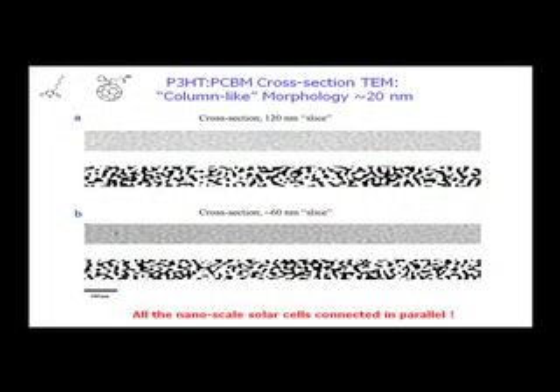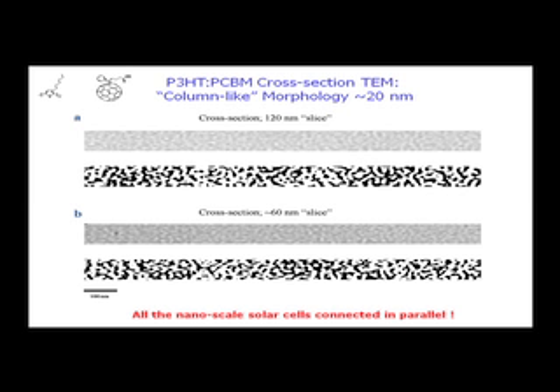Now, the data are here and here, here and here. This is for a 120 nanometer thick slice. This one is thinned down to about 60 nanometers. A little hard to see. We purposely just enhanced the contrast. This image to this one, this image to this one. We know that we have approximately 1-to-1 of the fullerene with the polymer. So we just made the volumes that we see here equal. That sets a threshold, and very easy to do. But you know, there's no cheating. Let me just find something that I can recognize. Look at this structure here. You see it very nicely here, and you can find it all over.